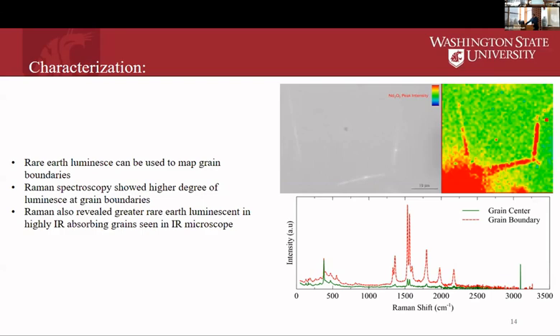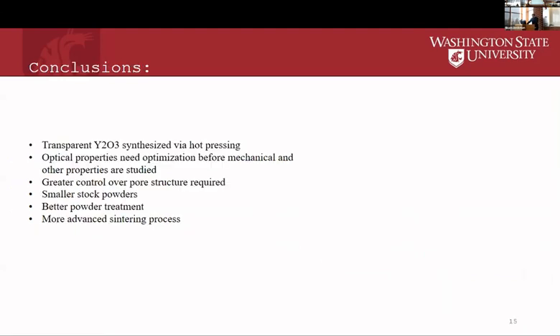We've done rare earth mapping with the 785 nanometer laser, and you can clearly see where you have a much higher concentration of this neodymium luminescence. It's very interesting to see that. We can also see that not all grains in our sample have a homogeneous amount of neodymium oxide or neodymium 3+ ions. We have one grain much higher in neodymium concentration, and one grain much lower. So it's important to see that.